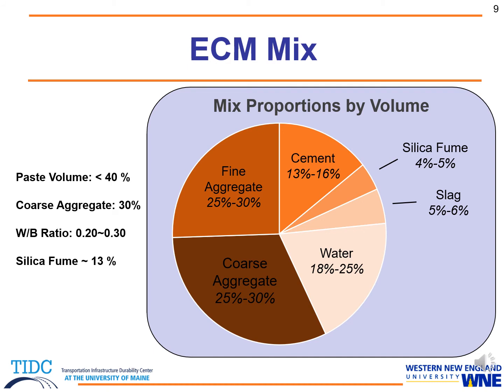So for cement, we've tested both type 3 and type 1. High strengths were achieved by type 3 and type 1 due to the heat of hydration. Some type 3 mixes were not able to be successfully mixed. Therefore, we switched over to type 1 and were able to achieve very good strengths. So type 1 cement was used for the remainder of our tests.